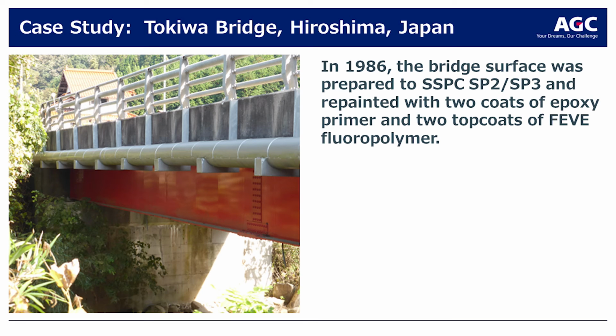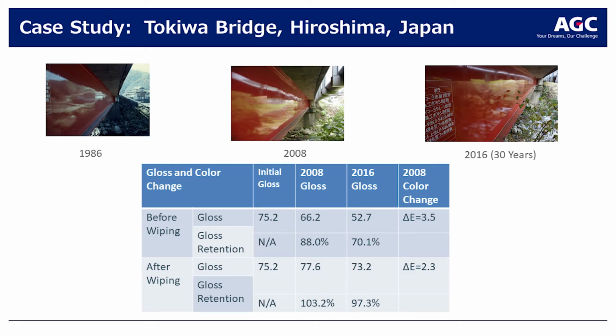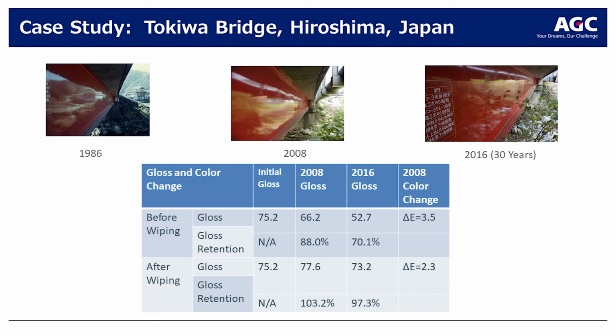Case study, this is a bridge in Japan. This was coated in 1986, and they looked at it for 30 years. They looked at the different properties of the material. What you can see here are photographs of the bridge over the 30-year period. If you look at the color change, which we call delta E, and the gloss retention of the cleaned surface, or after wiping especially, because the dirt does accumulate on these things, you can see it's outstanding color retention. Anything less than 5 on the color side is barely discernible to the eye. And the gloss retention after that 30 years is also excellent. So that's a good indication of the long-term performance.